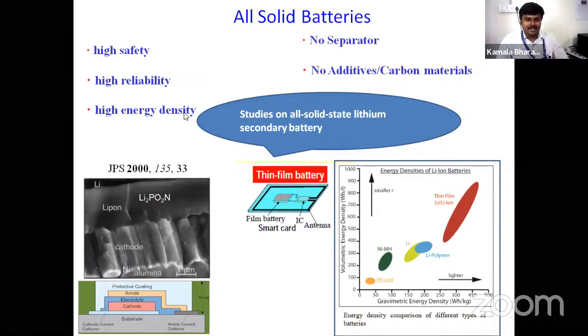have high energy density. So this left hand side image shows the first thin film battery prepared by Oak Ridge National Laboratory, and this right hand image will tell you how the energy density can be increased. You see here the gravimetric energy density compared to the present lithium battery, you can enhance to more than 300 watt hour per kilogram when we go to thin films because of its low weight.